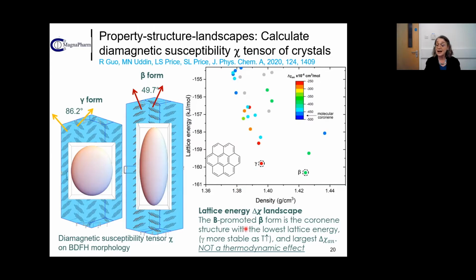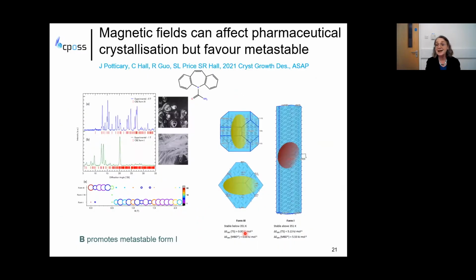But actually, we also found out in this process that the beta form is the low temperature form that nobody had been able to solve at all. And what we'd actually observed was we'd crystallized out a metastable form at room temperature. But we did try this, and yes, magnetic fields can affect the crystallization of pharmaceuticals.